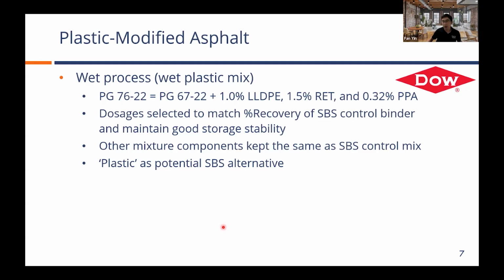Also, because of the terpolymer introduced, we are adding PPA just to speed up the chemical reaction between the terpolymer and asphalt binder. So if you look at the information here, now you understand why I said, even though we call it wet plastic, it's really not just plastic. It's a hybrid polymer system that includes the plastic as part of the picture. You may wonder, how did we determine the dosage?